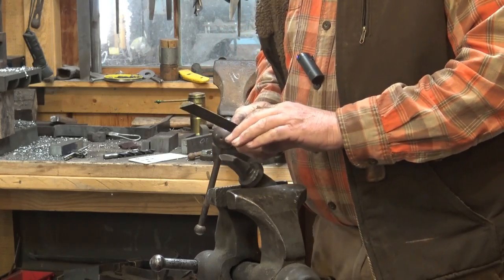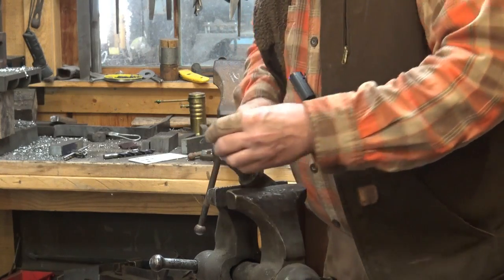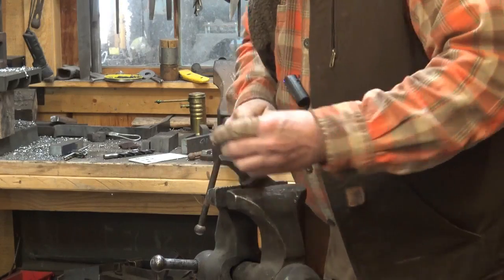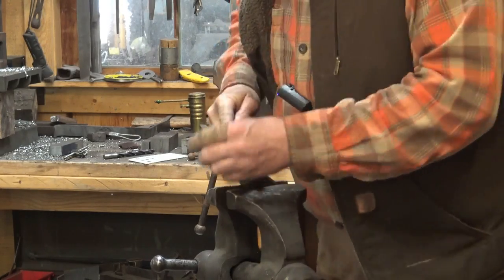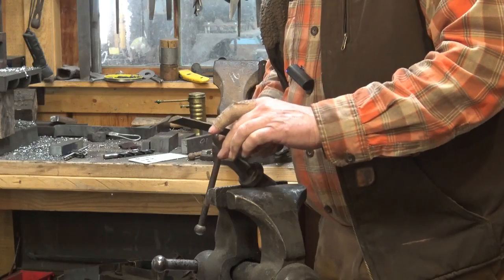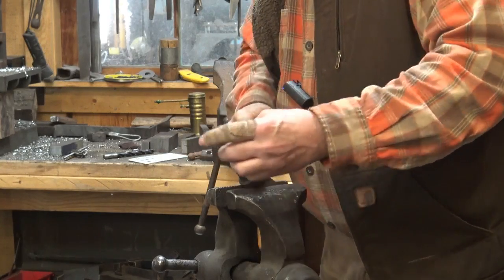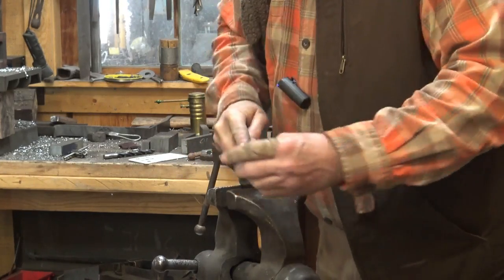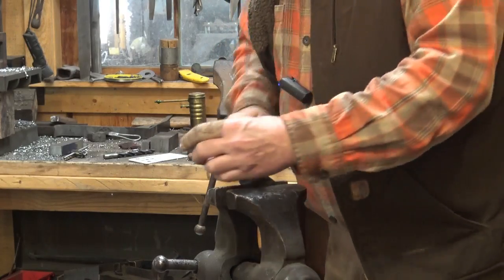After tempering, this should be just soft enough that you can sharpen it with a file if you need to. If it's still too hard to sharpen with a file, you probably need to temper it some more. Not longer, hotter.